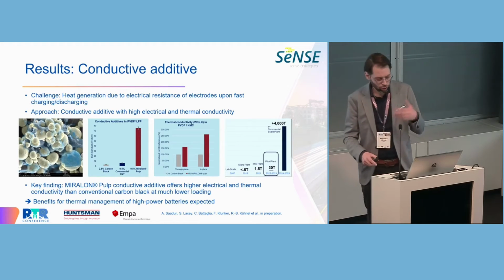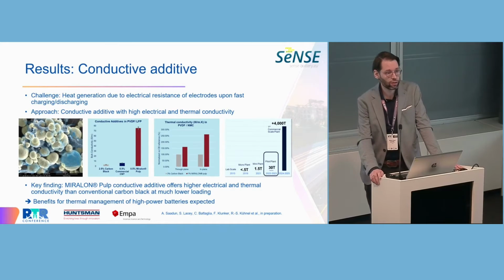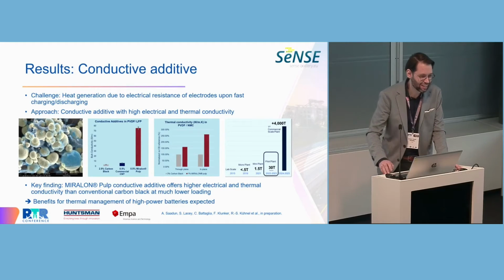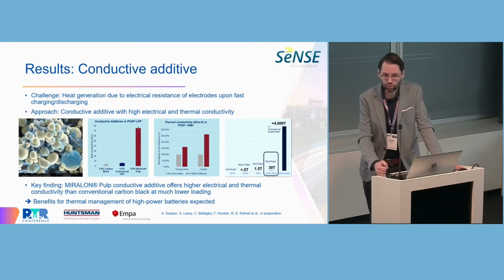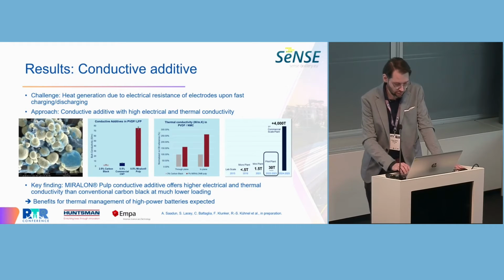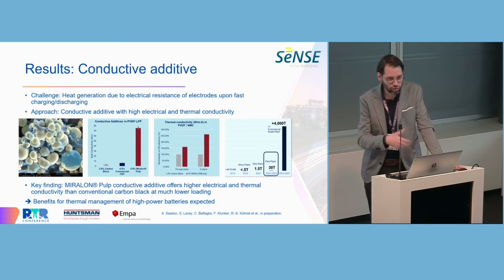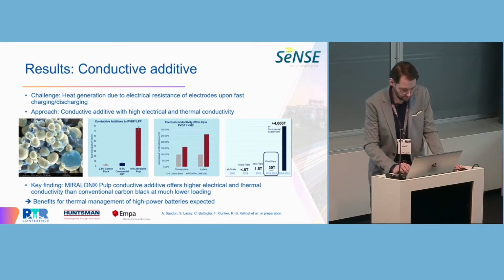And we also built cells with this material, and it actually ended up in one of our demonstrators. And we obtained a very similar cycling stability compared to carbon black. And our industrial partner Huntsman in the project just commenced the construction of a 30-ton plant in the US, not in Europe, but still producing this carbon material in increasing quantities. But as far as I know, they're planning to make formulations with this carbon material in Europe that they then want to sell to, for example, cell manufacturers.